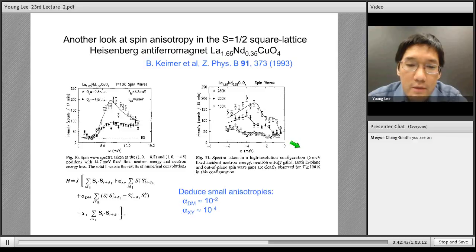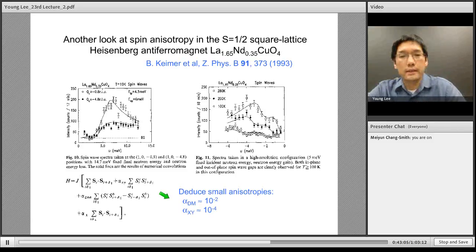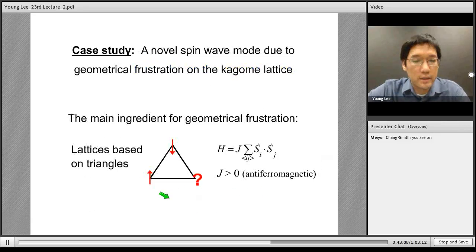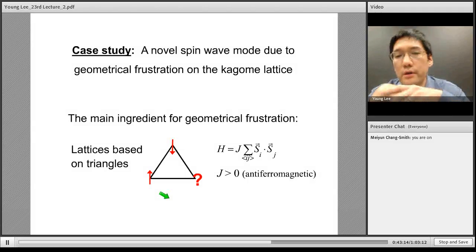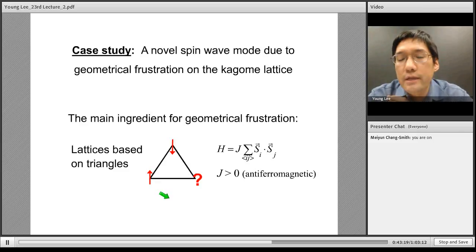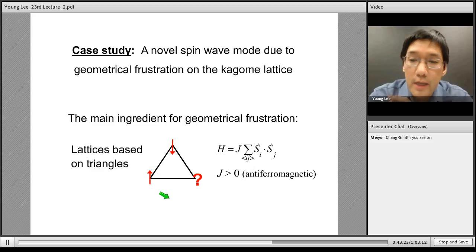And if you just look at this high temperature data, for example, you can see that you do have these two peaks here, and those two peaks do move as you cool down. And you can deduce what these anisotropy terms are. And they're very small, 10 to the minus 2 and 10 to the minus 4 in this important copper oxide material. Okay, so those are ways neutrons can tell you about terms in your spin Hamiltonian, but more or less looking at conventional spin wave modes that we expected from the Heisenberg model.